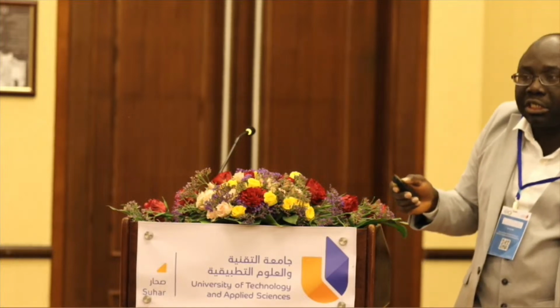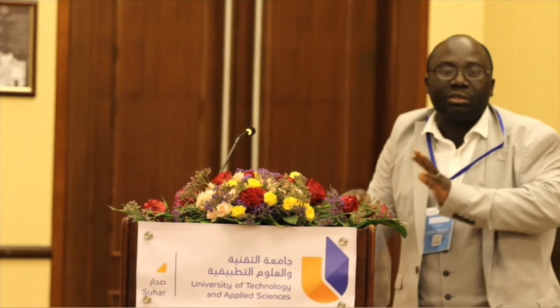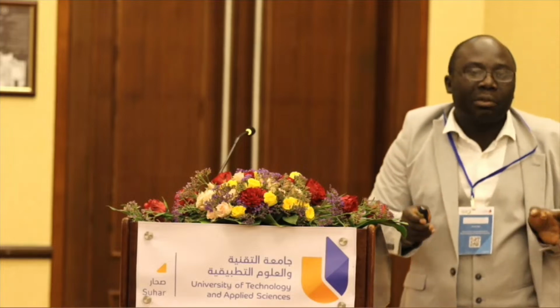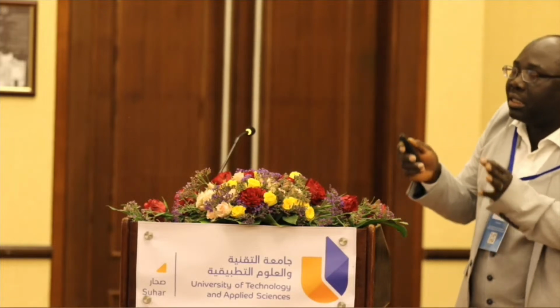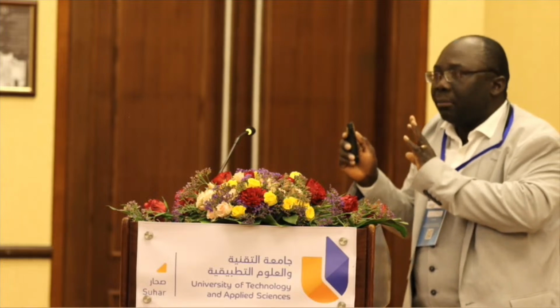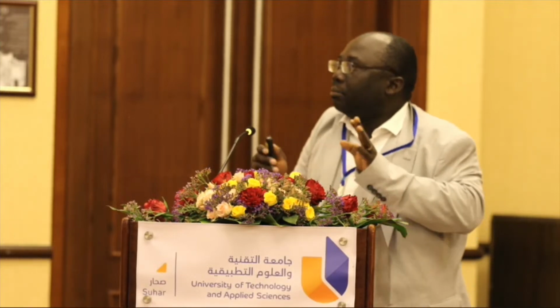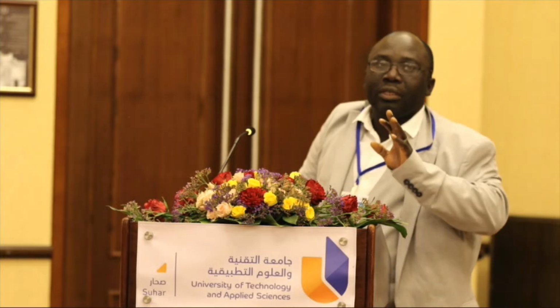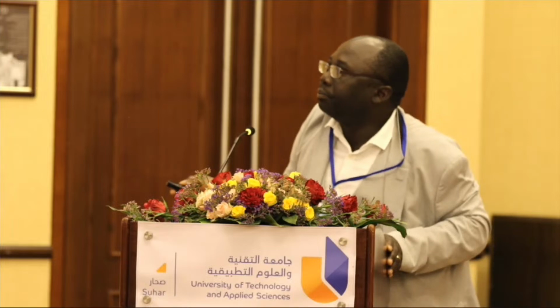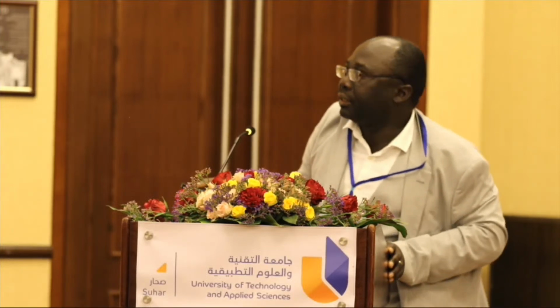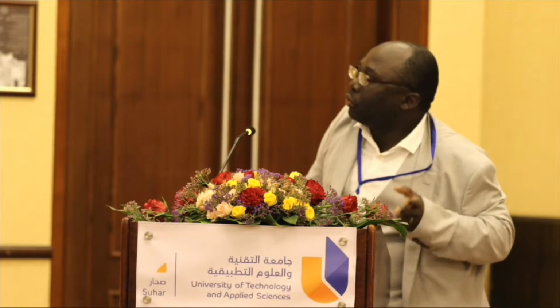The problem with microwave heating, however, is that it's extremely difficult to scale it up. So the microwave you have in your kitchen, to be able to scale it and use it in the industry, it's very challenging. And this is partly because temperature measurement with microwave heating is very difficult and challenging. And apart from being challenging, heat distribution is also usually poor with microwave heating. Then we looked at pyrolysis.